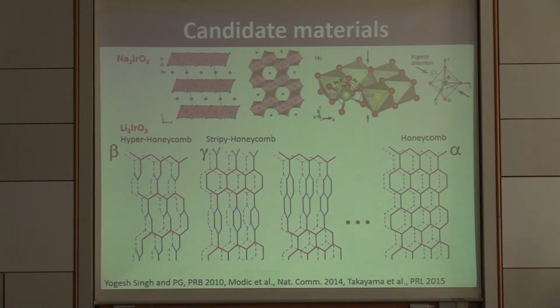The same structure is also realized in lithium iridate, where we just replace sodium by lithium. But the lithium iridate has the speciality that we could also have rotations of these honeycomb planes along the third direction, and we can get to three-dimensional versions, mentioned in the previous talk, which also fulfill the condition of having threefold coordination of the local magnetic sites and the edge-shared IrO6 octahedra.